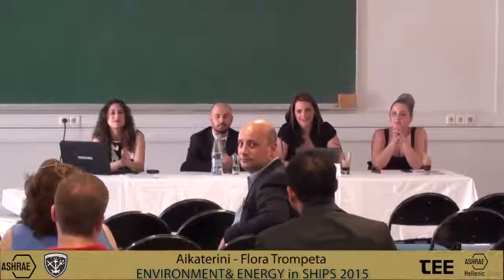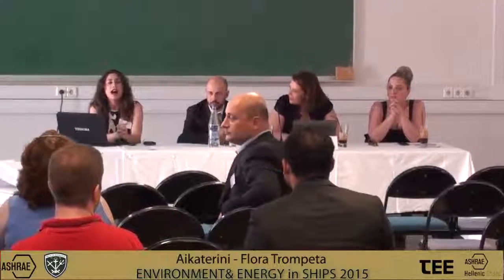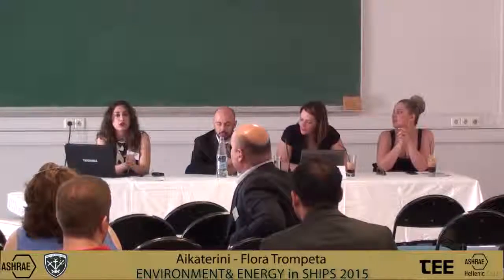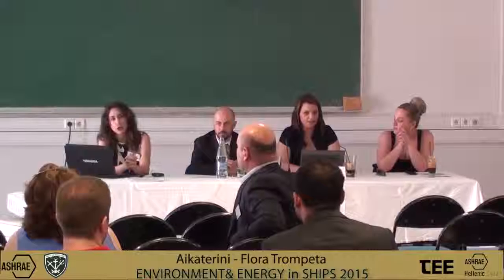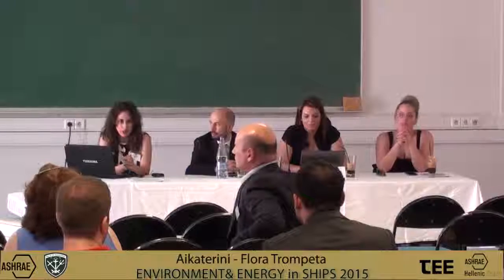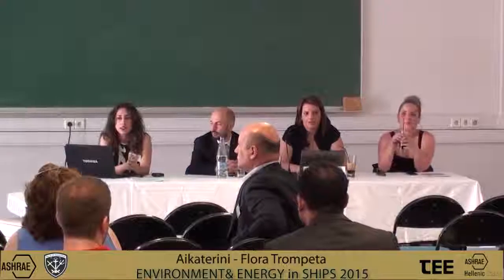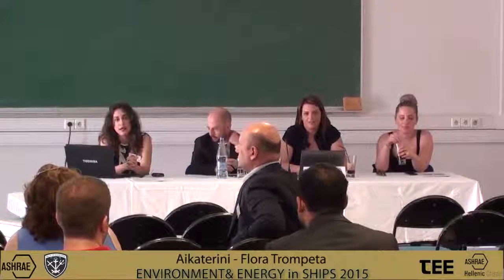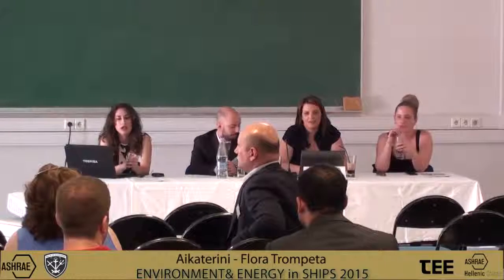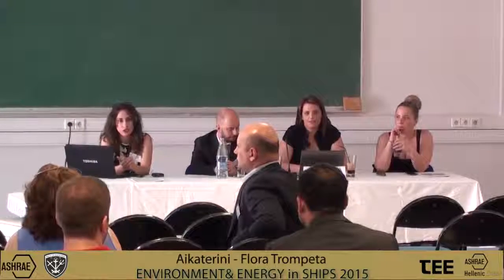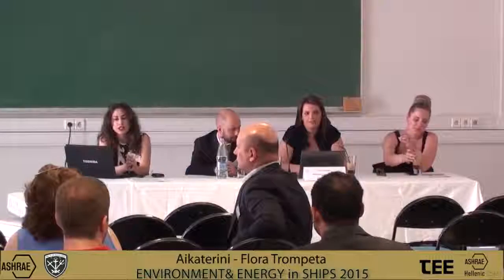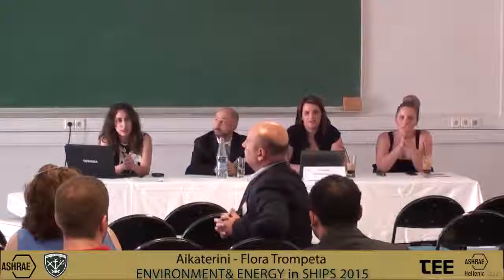Please. Yes? Have you studied the effect of roughness? We have also made a lot of measurements with optical microscopy or with nanoscratch test about the roughness of the coatings. It is very crucial to see the roughness. When we had the concentration of 0.4% of CNTs, the roughness was very increased, and this is why maybe we also have problems with anti-corrosion performance. The concentration of 0.2% was the ideal.